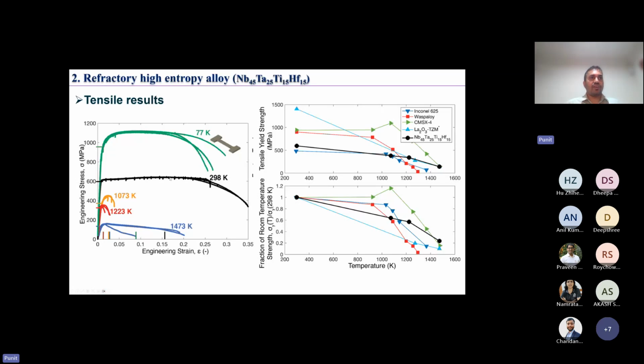At room temperature, it shows uniform strain of about 15%. Even at cryogenic temperature, this material is ductile, and we see uniform strain of about 10%, which is really surprising for a BCC refractory material. At higher temperature, BCC materials lose a lot of ductility because of intergranular fracture, as I will show in the next few slides. But we see that this material fractures only after yielding, even at 800 degrees C and 950 degrees C. And at 1200 degrees C we also see the material yields before it fractures, and we see strain softening happening here.